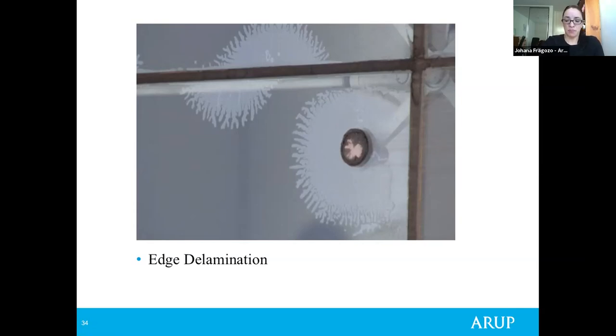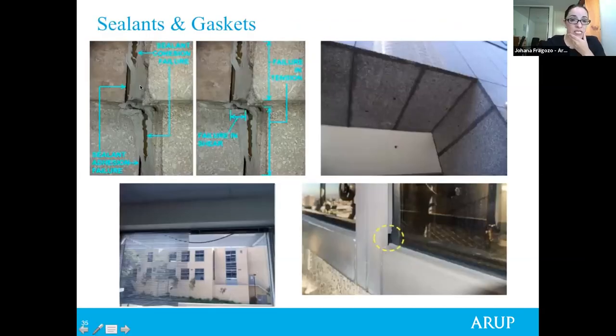With sealants, the typical types of failure are cohesion failure, adhesion failure, and failure in shear. Due to aging, the sealant can become a little bit tacky. It turns again into this sort of moist condition where it loses its strength capacity. With gaskets, the most common defect that we see is the dropping of gaskets, and this could be due to thermal expansion of the different elements of the facade, or due to aging of the gasket and therefore shrinking. We also see a lot of shrinking of the ends of the gaskets, and again it's due to weathering and just aging.